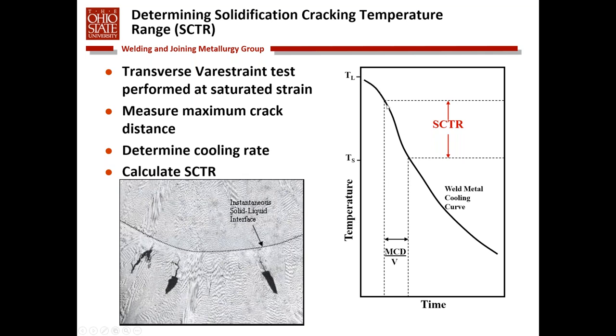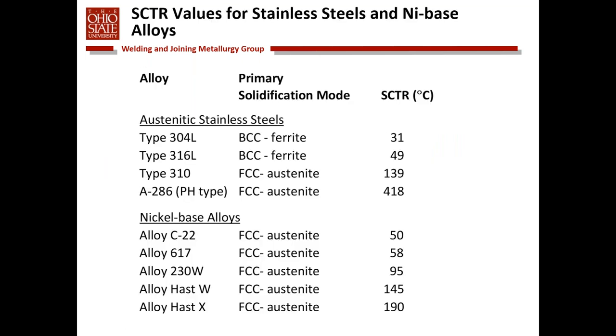So this is the cooling curve as the weld cools from the liquidus temperature through the solidification temperature range. That gives us a value of solidification cracking temperature range, SCTR, which is similar to the BTR, brittle temperature range, and is an actual measure of the temperature range over which cracking occurs.